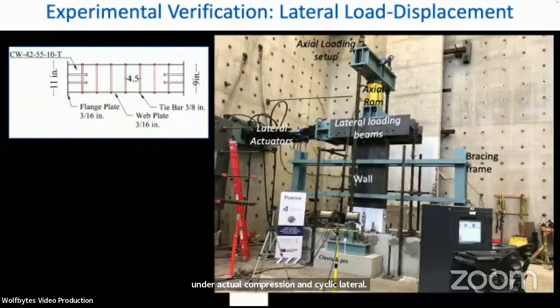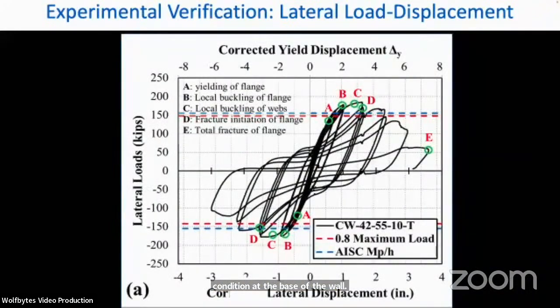You're also noticing the fixed condition at the base of the wall, and this is the location where plastic hinging will form. In summary, this is the lateral load versus displacement response of the specimen that I just showed you. And what I've done is gone ahead and identified the occurrence of various events along this load displacement response: the yielding of the flanges, local buckling of the flanges, local buckling of the webs, fracture initiation in the flanges, and then finally, total fracture of the flanges.